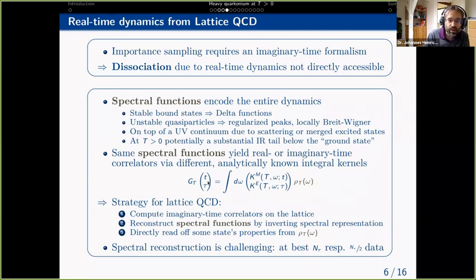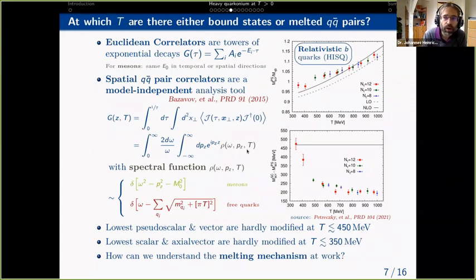Now, doing this inverse transform from the correlation function here to the spectral function there is quite difficult because we typically have order 10 or maybe 20 points for the correlation function, but we need to know the spectral function with at least order hundreds to thousands of different points in frequency space in order to get a precise picture of some relatively sharp structures. And so this spectral reconstruction is a very big challenge, and this is still not something where we have final answers in all cases. So there is one way to slightly circumvent this, and that is something that I want to discuss here.